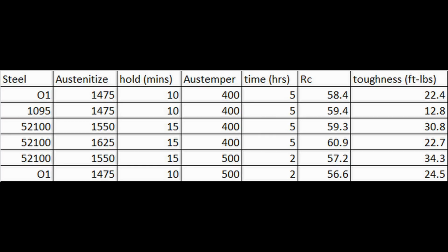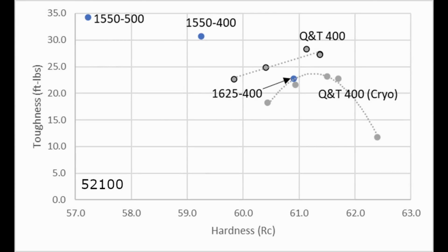Okay, so let's get to the properties. So I've got the 1550 500. That's the pretty standard high hardness Austemper for 52100. I got just over 57 Rockwell, a little bit lower than was shown on the TTT diagram, but not too crazy. The 1550 with a 400 Austemper was just over 59 Rockwell, and had a little bit less toughness. But if we were expecting a big difference in toughness by having 50% martensite, we did not see that in this case. Then when I used 1625 and a 400 degree Austemper, I got just under 61 Rockwell, and the toughness was basically equivalent to other experiments I had done with quench and temper 52100.